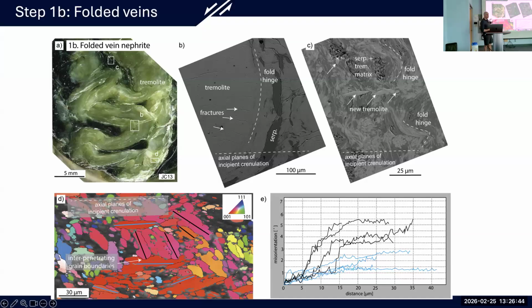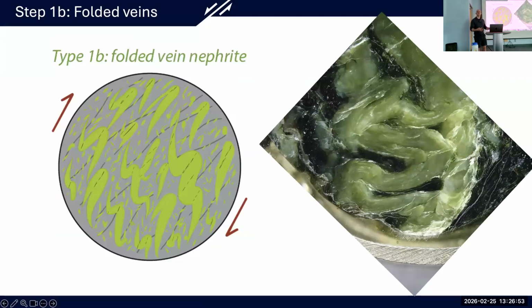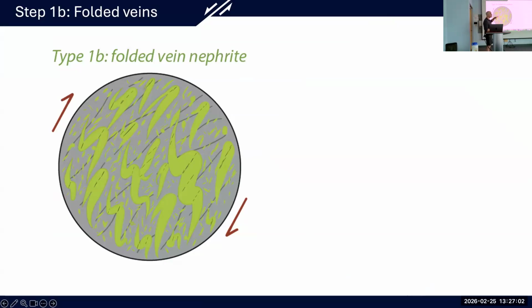And while this is happening, we also have the growth of new tremolite grains that are forming within this. This kind of gives us our second step to the process, the folding of our veins. Now, if we allow this folding to continue to take place, grow new grains, and essentially replace all of the tremolite, perhaps through continued veining and mineral growth, eventually the rock will be entirely comprised of our tremolite, our nephritic-like fabric of tremolite. Now, we're not yet quite at a perfect, complexly interpenetrating fabric like we saw before.